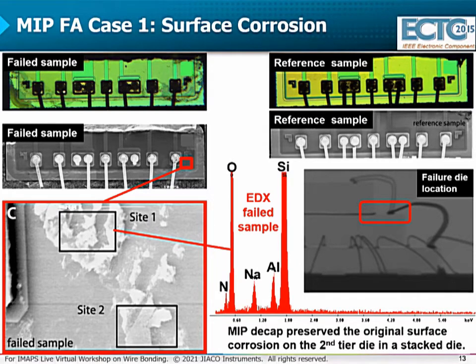Now, after MIP decapsulation of the failed sample, it was already obvious with the optical microscope that there was this suspicious topography on the second die. SEM imaging further revealed that there was a thin layer of foreign material present at this location, and EDX analysis on the same location showed traces of sodium and aluminum. Sodium obviously originates from the saline that we introduced, and aluminum possibly occurs due to corrosion of the aluminum bond pad. So to conclude, here MIP technology proved its unique capability to preserve original surface corrosion in a complex 3D stacked die package.